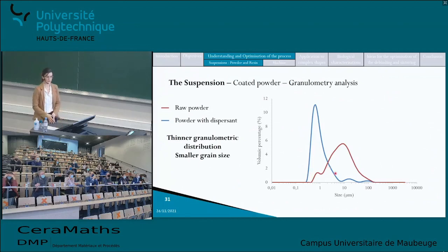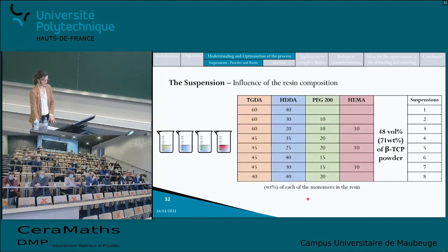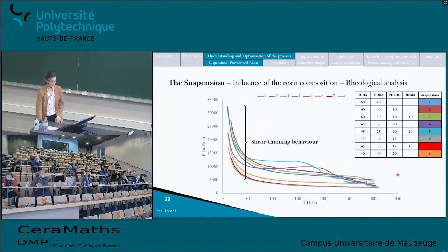The next step was to evaluate the influence of the resin composition on the properties of the suspension and the printed parts. So with the 4 monomers that I selected, I varied the composition using always the same amount of powder, which was 48 volume percent of β-TCP powder. So I first evaluated the rheological behavior of all of the produced suspensions, and I realized that all of the suspensions presented a shear thinning behavior, meaning that the viscosity decreases with the increase of the shear rate.